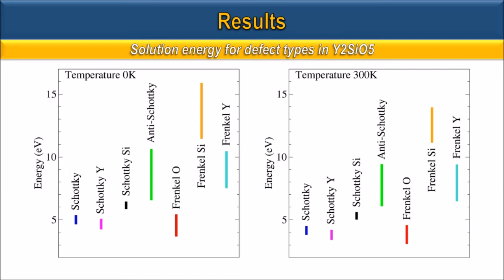Well, the nature of intrinsic emissions in lutetium silicate and yttrium silicate, although not fully understood yet, can be partially explained considering that oxygen Frenkel pairs are formed in the materials and the oxygen interstitials will sit in a position loosely connected to neighborhood silicon species, leaving the possibility for this ion to anchor the electron-hole pairs.